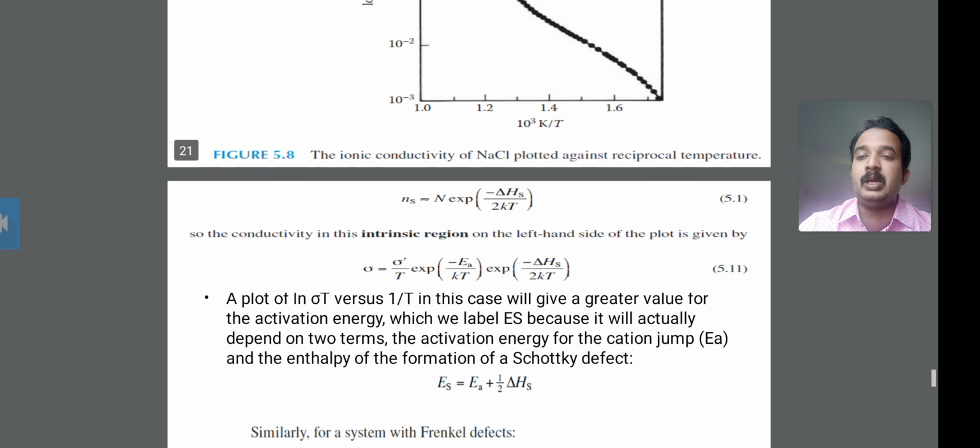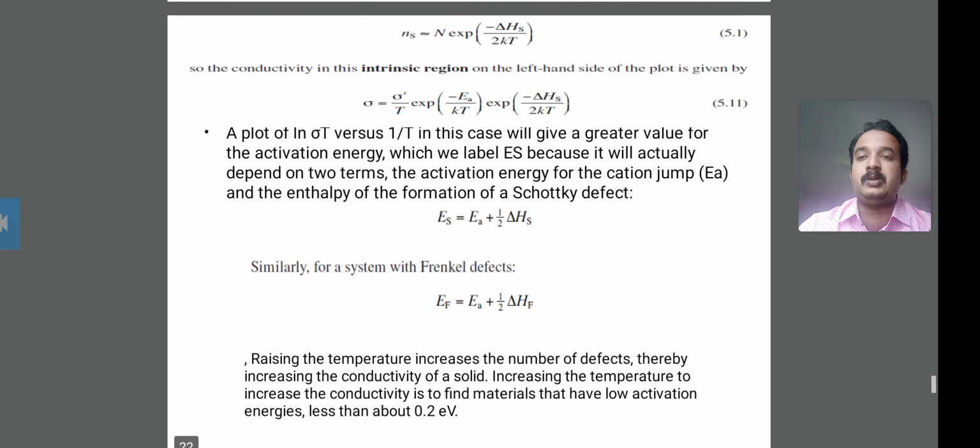Then you also have to know the formula for the number of Schottky defects. The derivation we will discuss in the concentration of defects. Look at this formula for the number of Schottky defects: Ns equals N exponential of minus delta Hs upon 2kT. This is the number of